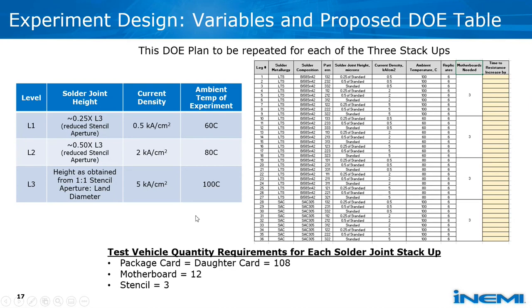The solder joint height will be varied by varying the amount of solder paste printed on the land before SMT reflow, and that solder paste will be varied by changing the stencil aperture. The table is shown there. Since it's a 3x3 design, it's 27 legs. We also added the SAC legs for comparison. But because the SAC solder has a much slower electromigration than LTS, only the legs with the 100 degrees C temperature have been added. And below you can see the number of package cards and daughter cards that are required for this test. And I will go into what is a daughter card and package card and motherboard shortly.